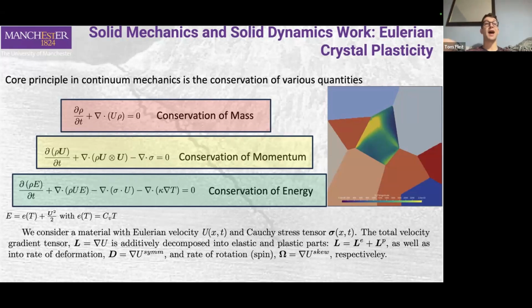But actually, what happens if you have very high strain rates and very high strains is that the mesh can become so deformed in a Lagrangian approach that the computational points, or the elements where you solve these equations, can basically smash through each other. What you would see if you ran that solution is that people would say the solution blew up, or the code failed. But actually, when the code tries to take the spatial derivative to solve these equations, it returns an infinite number, because the mesh has gone through itself. So in those cases, it's much better to use a Eulerian approach. We've developed these Eulerian approaches for plasticity, which are really novel. No one's doing this, for various reasons. It's expensive, and it's difficult, basically.